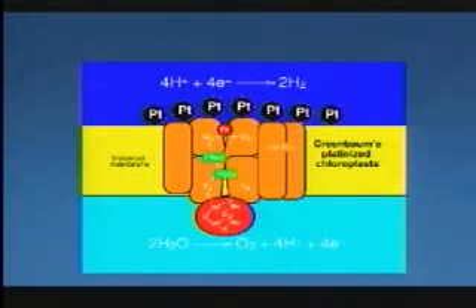You can put platinum on one side. Eli Greenbaum at Oak Ridge has done this, and take the reaction center and manganese and photosynthesis on the other side. And this evolves oxygen, just like plants normally do. And this co-opts the system to not make NAD and NADH, but it makes hydrogen on that side. And this actually works for a little while. The platinum later on actually just hydrogenates all the organic matter in the plant, and this dies. But it would be good if we figured out another way to do this that didn't use platinum. We don't have a way to do that yet.